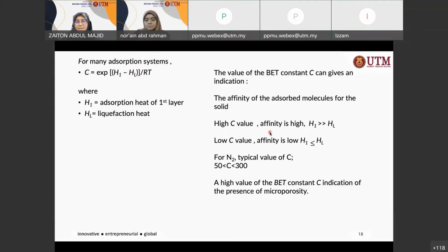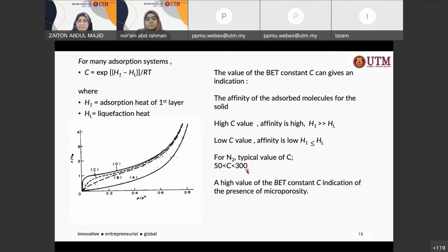A high C value indicates a very high affinity between the solid surface and the adsorbate gas. A low C value indicates a low affinity between the solid surface and the adsorbate gas. If you're talking about nitrogen, the typical C value will be between 50 to 300. A high C value is also an indication of the presence of microporosity. So if your C value is very high, more than 300, then there is a possibility of having micropores. So you go and have a look at your BJH desorption to see whether you do have micropores or not. If you do have, then you have to run the alpha-S plot or the t-plot.